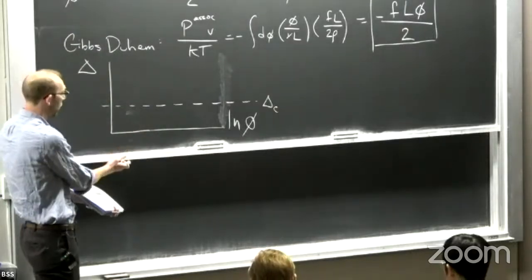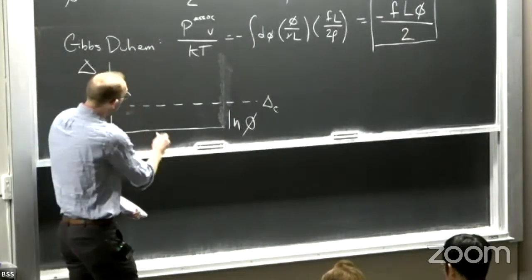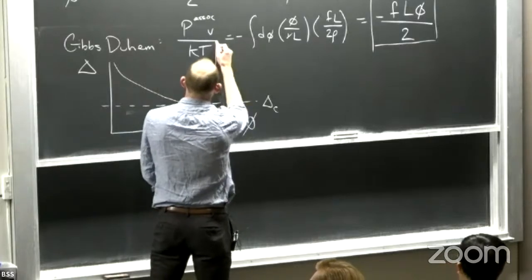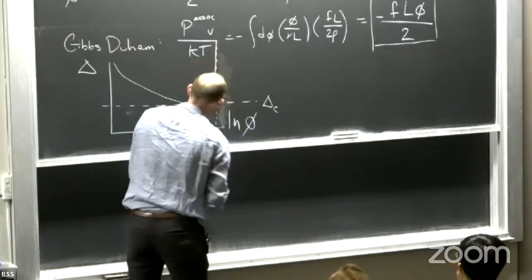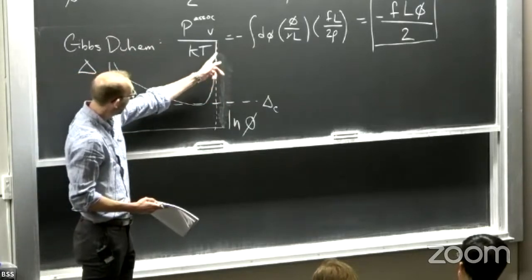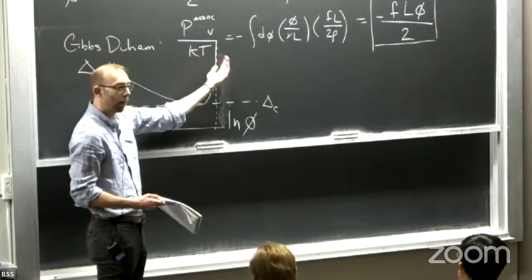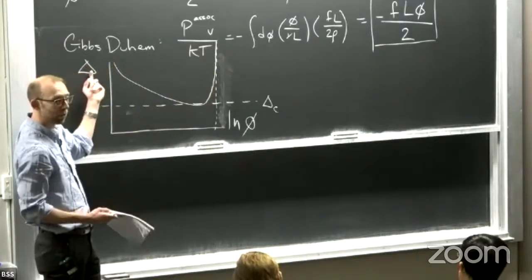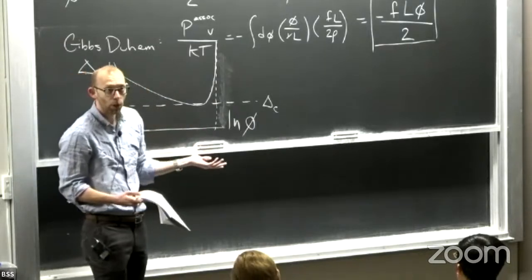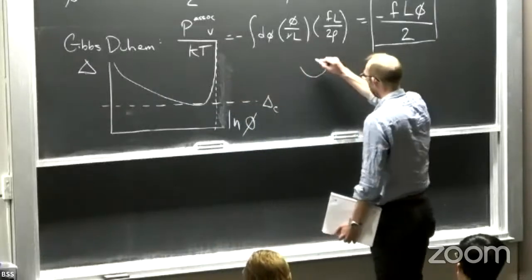If the association parameter is stronger than that, we can have phase separation. But what is interesting here is that this tells us that we're going to have a condensed phase volume fraction that becomes a constant as we make this interaction very, very strong. And that constant can be less than 1. So you can end up with a system that looks in the condensed phase like this.